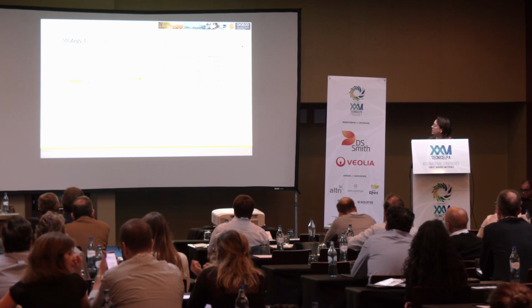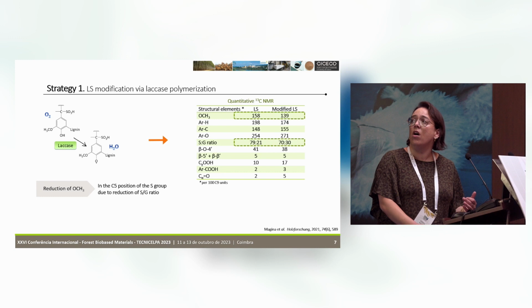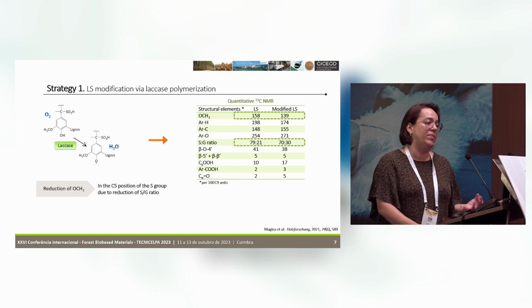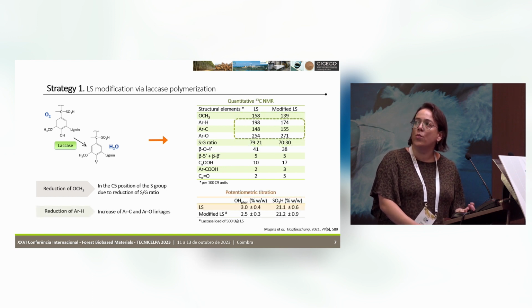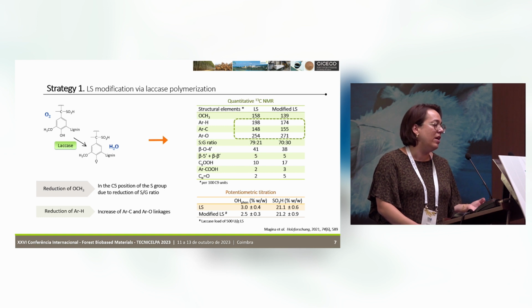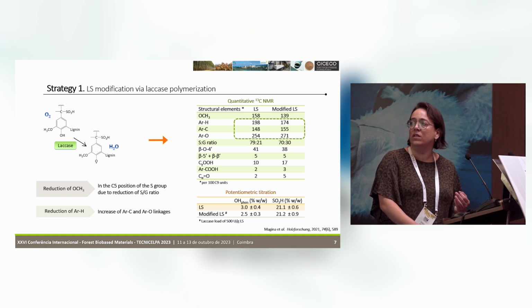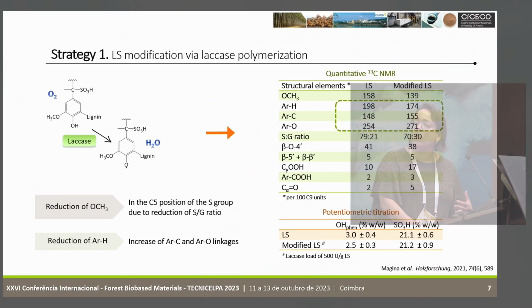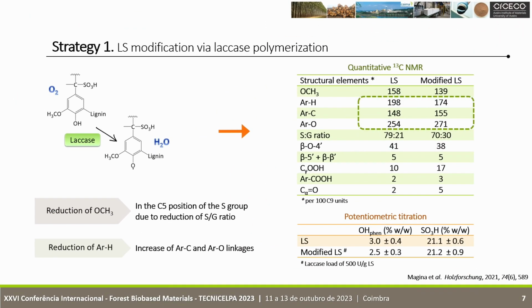The best condition provided a product with an 11-fold increase of the molecular weight, still soluble in water. Comparing the structure of this modified product and unmodified lignosulfonate, there was a significant reduction of the number of methoxyl groups and significant change of the S/G ratio of the product, with the decrease of S structures, most probably in the C5 position. Also, there was a decrease of the tertiary aromatic carbons along with the decrease of the number of hydroxyl groups, but also an increase of the quaternary and oxygenated aromatic carbons.